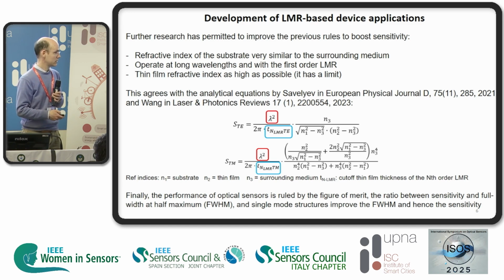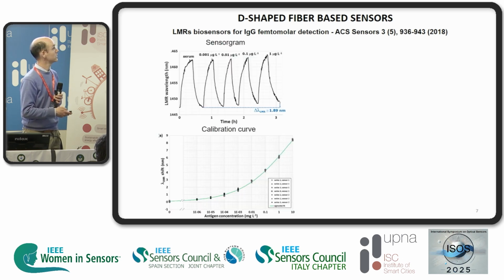And it has been observed, not with these analytical equations, with more advanced equations, that the full width half maximum is decreased when we operate with single mode structures. So that is why, for instance, we will see now some results with D-shaped fiber sensors, which are single mode structures. We get very good results. Here I show some examples. The femtomolar detection of IgG with a D-shaped fiber sensor.